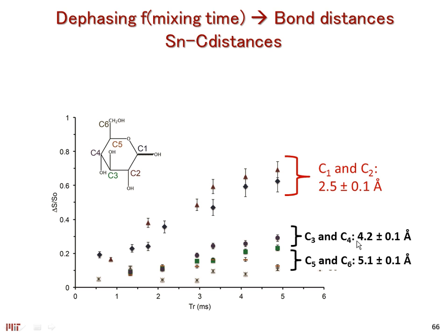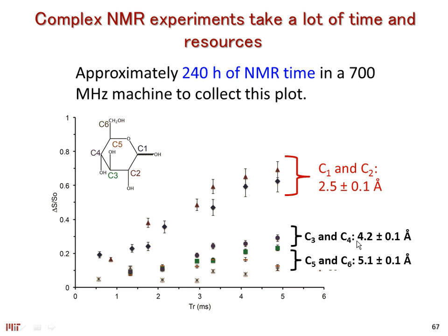Of course, when we do these types of experiments, they are actually very elaborate. They're very time-consuming, and we are very fortunate that we have this center called the Francis Bitter Magnet Lab, where we can perform a lot of these solid-state NMR experiments for long periods of time. For example, to collect this graph over here that I'm showing you, this took about 240 hours of NMR time. And you can imagine that this is extremely expensive to do unless you have some buddy like Bob Griffin in my case that allows you to use these machines for a while. So this is 10 days of straight NMR time in a 700 megahertz machine. So this is a lot.